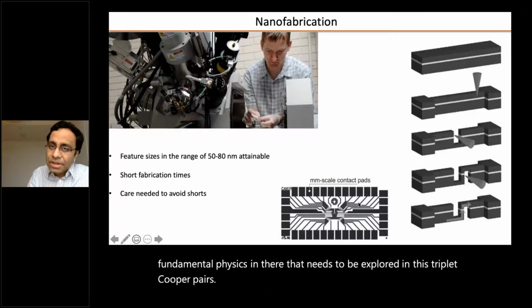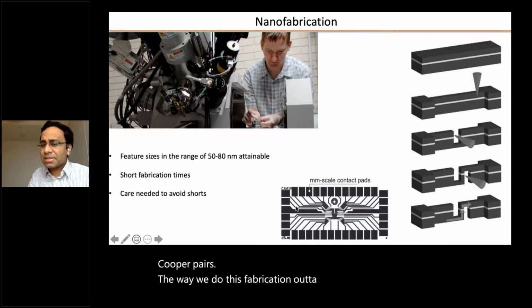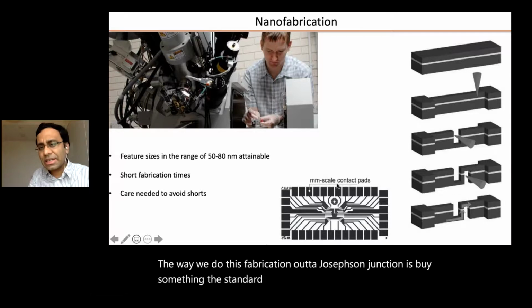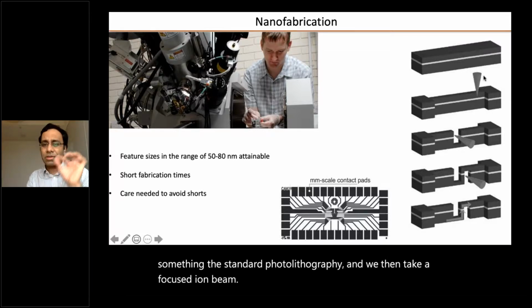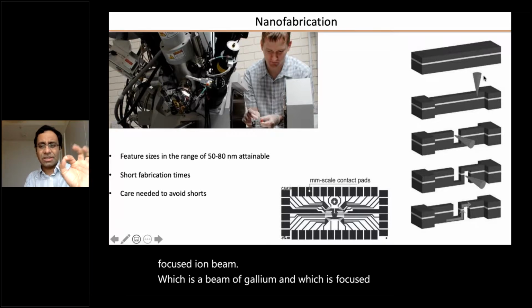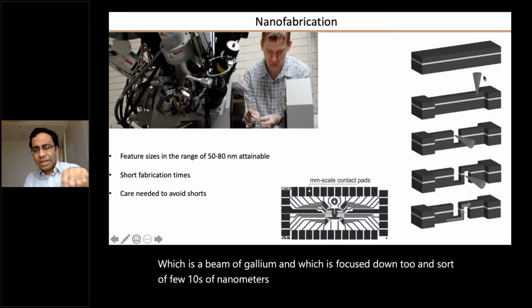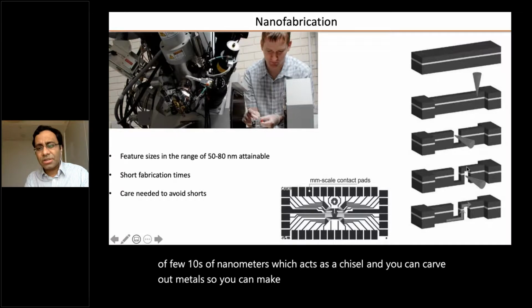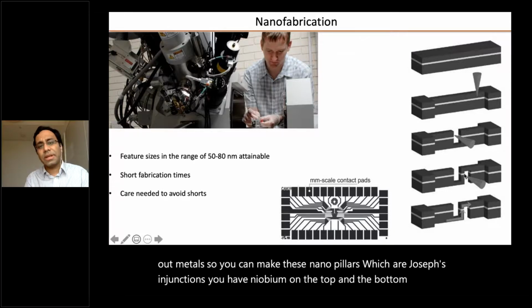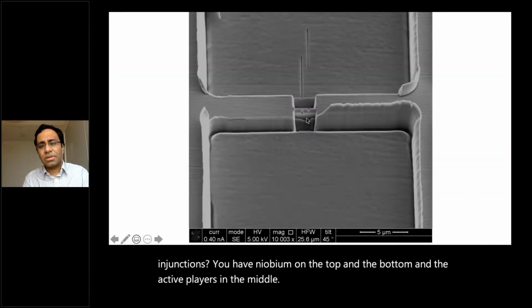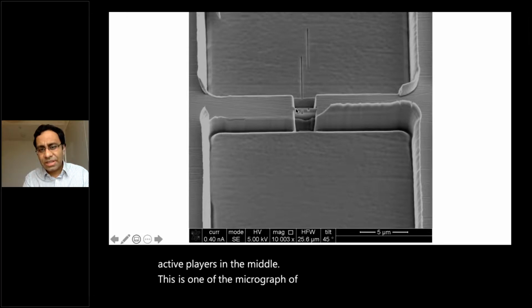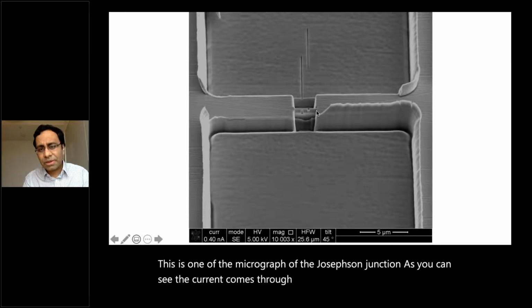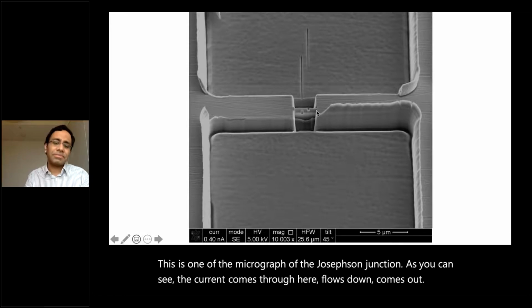The way we do this fabrication of the Josephson Junction is with standard photolithography, and we then take a focused ion beam, which is a beam of gallium ions focused down to a few tenths of a nanometer, which acts as a chisel, and you can carve out metals. So you can make these nano pillars, which are Josephson junctions. You have niobium on the top and the bottom, and the active layers in the middle. This is one of the micrographs of the Josephson junction. As you can see, the current comes through here, flows down, comes out. So these are very easy to make.